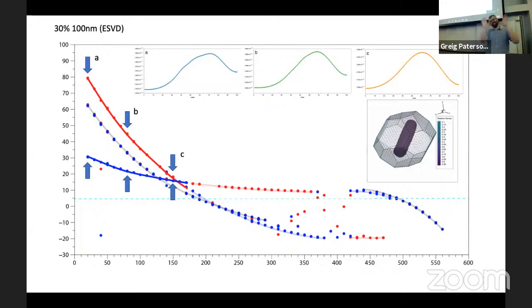It can support two basic types of domain structure, one of which is one of these perpendicular things that I was talking about, and then one that's parallel along the axis of elongation. But the energy barriers are asymmetric. And so what you're going to see in this thing is some really complicated thermal behavior. The speculation is, as you heat this and go up and down, what you're seeing along the bottom, the axes are not labeled, is temperature, and on the side is the logarithm of